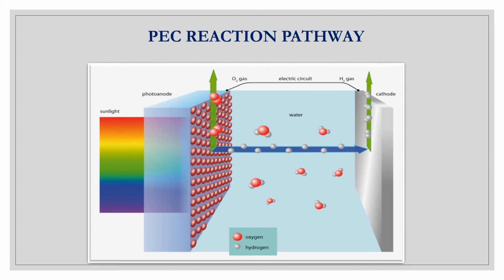In detail, when the photons, that means the energy from the sunlight, are absorbed by the catalyst, the water will split into hydrogen and oxygen through redox reactions, that is two half cell reactions. The water usually oxidizes at the anode to produce oxygen gas, whereas at the cathode the hydrogen ions are reduced to produce hydrogen gas. However, in order for the reaction to take place, the selection of semiconducting materials, that is the catalyst, is very crucial. In the present work, the phosphorus doped MoS2 was selected and used to evaluate the hydrogen evolution reaction activity.